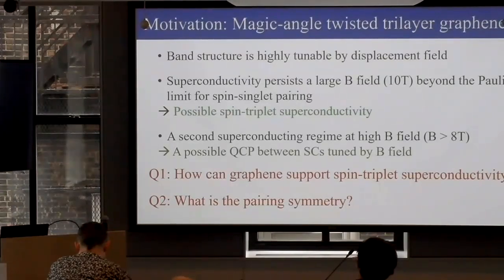Now the last topic, which I want to talk about, because this is electron-electron, I said phonons are not. These 2 groups, Santa Barbara, Columbia, and MIT compete. So Pablo came up with a paper. It's all in Nature, where he saw superconductivity in twisted trilayer graphene, at more or less the same time as these experiments. Here he finds the band structure is highly tunable by displacement field. And he claimed it's spin triplet superconductivity from electron-electron interaction.